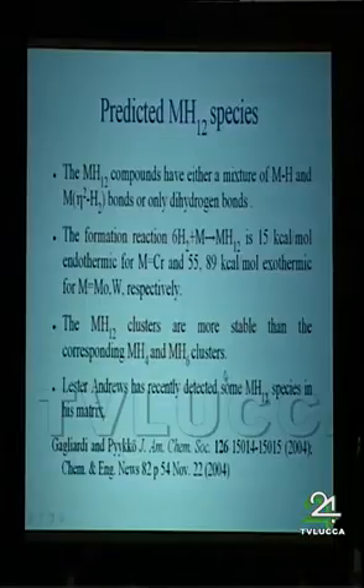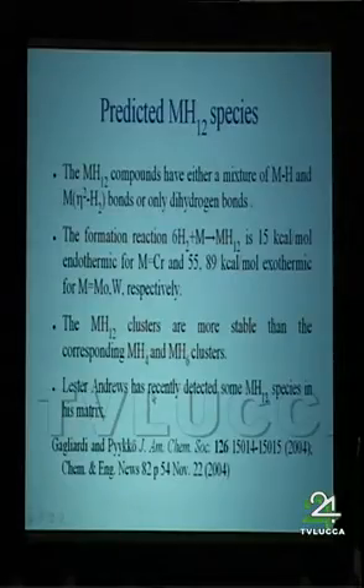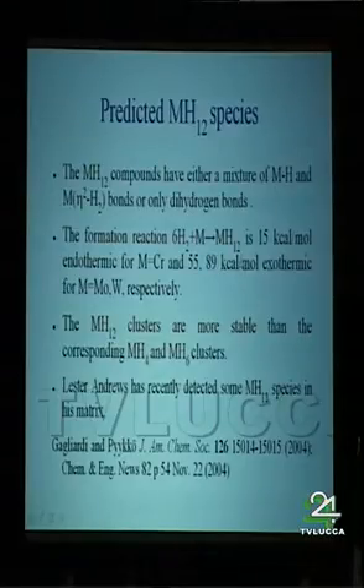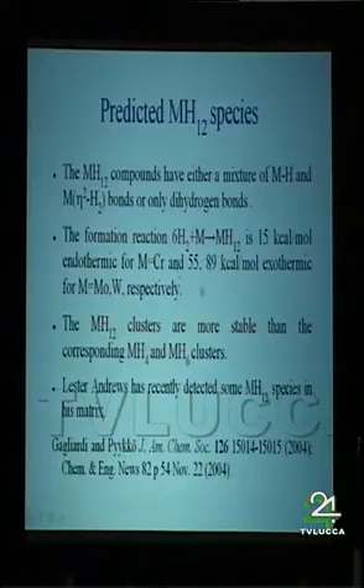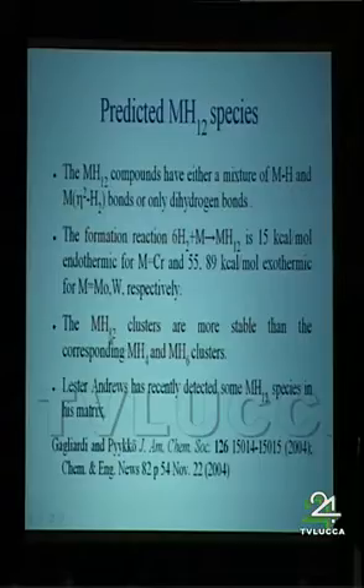We also try to understand a little bit about the energetics of these species. So what we usually do is look at simple formation reactions, like, for example, 6 hydrogen molecules plus a metal, which form this cluster. And it turns out that from very simple calculation, this reaction is endothermic when we use chromium, and it becomes exothermic when we use molybdenum and tungsten. So from a theoretical perspective, it would be easier to form the tungsten or molybdenum cluster than the chromium, but of course experimentally maybe it's easier to work with chromium than tungsten. And also these MH12 clusters are more stable than the smaller clusters like MH4 and MH6.